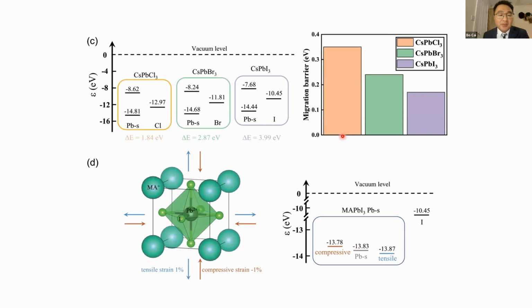Next, we check the band centers of these three lead-based halide perovskites and the corresponding migration barriers. The energy barriers EB rapidly decrease with the increase of the mismatch of band center levels. Then we apply tensile and compressive strain on the lattice. We also observe the same physical law.